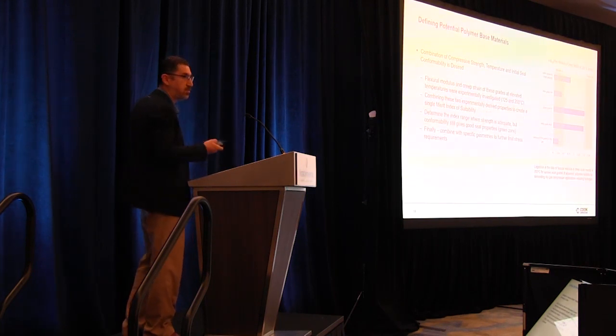But unfortunately, the selection process, or making sure they will work, is not very straightforward. So this is actually a graphical representation of the optimization game we are playing. I'm using a single merit index here. So I'm dividing the flex modulus I measured in the previous slide by the creep strain. So the higher the number, the better for us in theory. And I'm plotting all of my values for 5 different grades here. And again, we get the highest numbers with the PEEK and the polyimide. And I'm dividing the section into 3 groups. So you have the region A here, which is actually a collection of the materials that are not going to be tolerant to high pressures or high temperatures. So the PTFE is going to fall in this range.